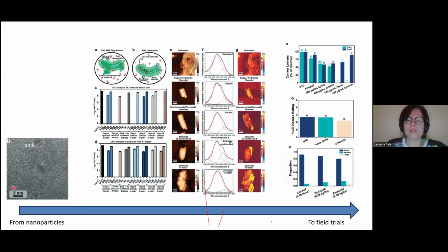So we worked with material scientists to understand the properties of the nanoparticle. We confirmed that their diameter is very small. Here is 2.5 angstrom. So there was a range of sizes, but on average less than 5 nanometers. And also we worked with neutron scientists and XRD scientists to confirm the crystallinity of the structure, the core-shell structures, and all of that. So we did a big part of material characterization for understanding the treatment.